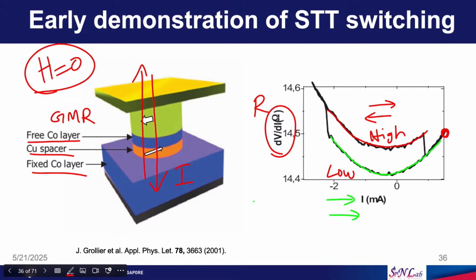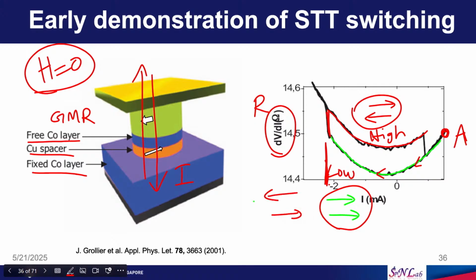Okay, so, let us say we start from point A in this picture and go towards negative current. So, we follow the green line path. Okay. So, at the starting point we are in the parallel state. So, when we go towards a certain current, say minus somewhere here, we can see that the resistance has changed. It has gone to a high value, which means at this particular current we have achieved the anti-parallel configuration, which means the magnetization of one of the layers has switched from being parallel to the anti-parallel state.